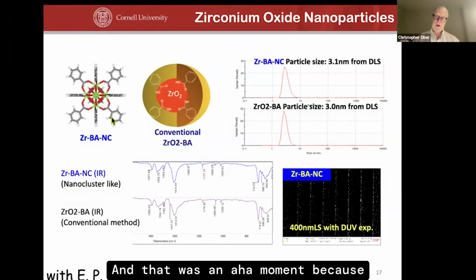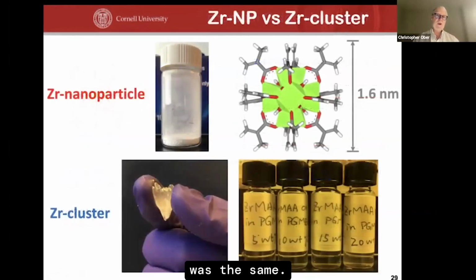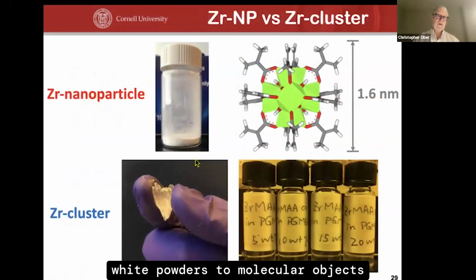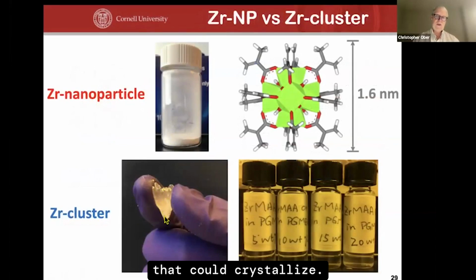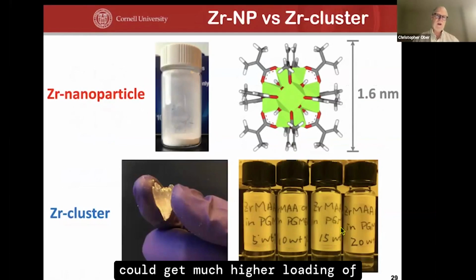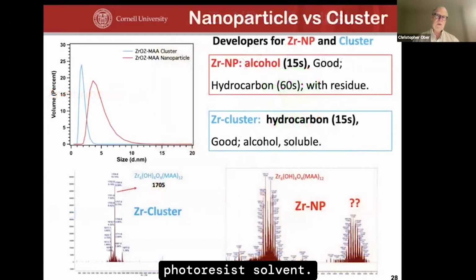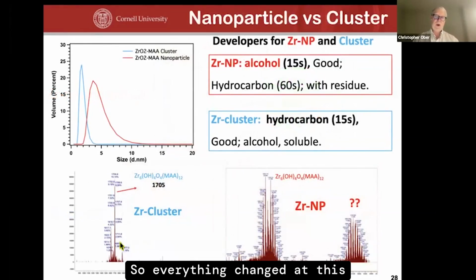And that was an aha moment because we were able to address the stochastics issue by not making particles with different sizes, some average size, but by making molecules with precise molecular composition and ensuring everything was the same. And so by golly, we went from these white powders to molecular objects that could crystallize. So this is a pure crystal of this molecule. The solubility went up, and so we could get much higher loading of these oxide particles, these oxide molecules in a photoresist solvent. And we also had, again, near molecular perfection. So everything changed at this point. We went from these kinds of structures that have multiple molecular objects to something that's pure.